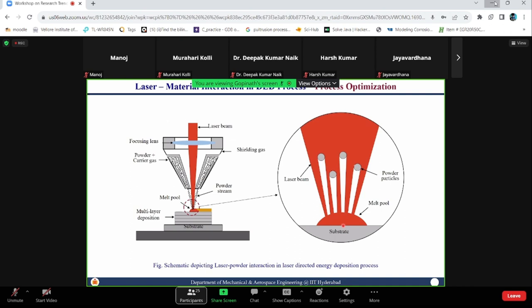What is happening is, let us say you have started depositing here and my pyrometer is taking the temperature from the center of this. Now you will come like this, and whenever the pyrometer comes here, the temperature goes up, right? And when the laser passes, it will start dropping down. Again, the heating at this position will only take place when the laser goes all the way to this point and returns back. In the time it takes to go from this point and return, it is cooling down. Our pyrometer can detect the temperature from 400 degrees centigrade. So before the laser goes from here and comes back, the temperature falls below 400 and you see a flat line.